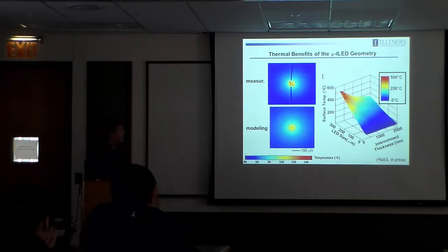The other advantage, I'll come back to this in a second, of very tiny small LEDs is the ability to do passive thermal management. Because the surface area to volume ratio is very high, the passive rates of cooling are very high, number one. And then number two, the electrical interconnects themselves have sufficient thermal mass that they suck heat away from the devices themselves. And so if you compute surface temperature as a function of LED size or interconnect thickness, you can see the tremendous benefits in going down in size and up in interconnect thickness. You can operate these devices at very, very low operating temperatures using those two concepts.